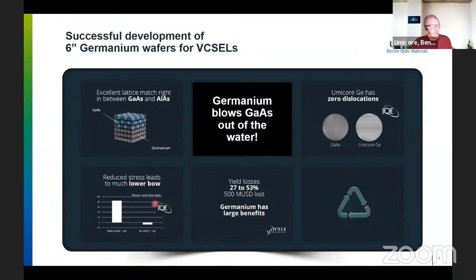And what you can see here is work being done by IQE, and they made an announcement last week on this work. This is work that's been going on for the last 2 years. What's important also is that this bow creates some issues in the processing, yield issues further downstream. And this has been calculated to be more than $500 million a year across the industry of yield losses that can be improved by using germanium.